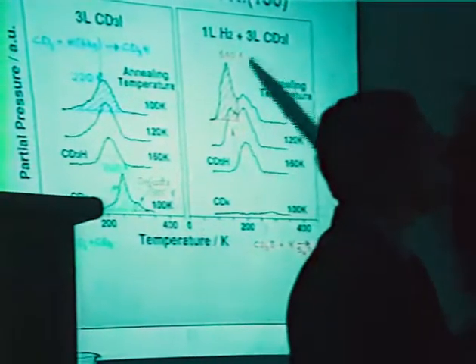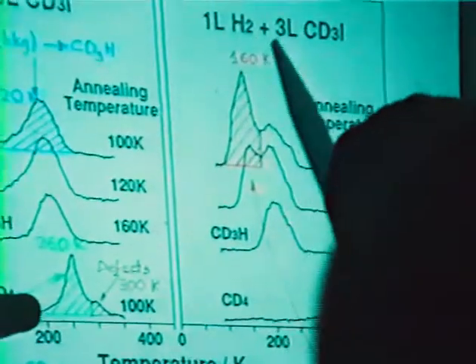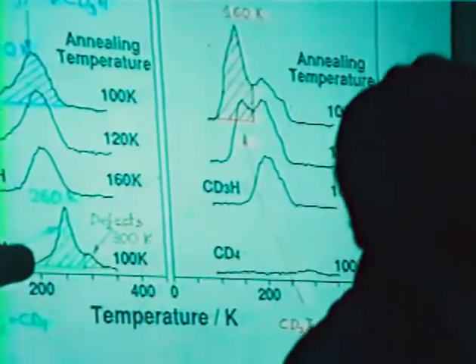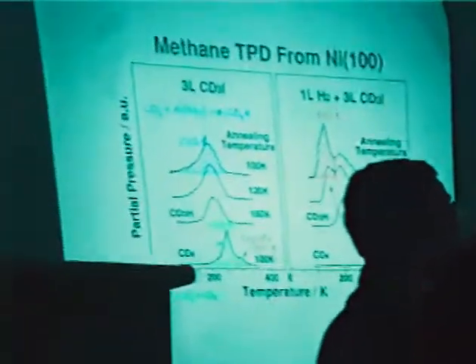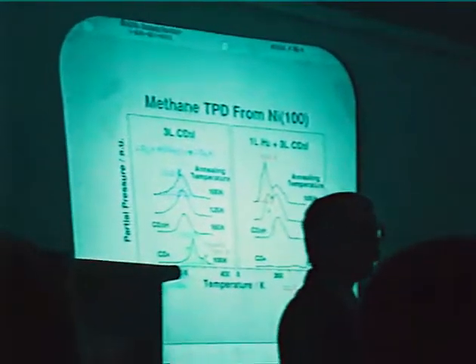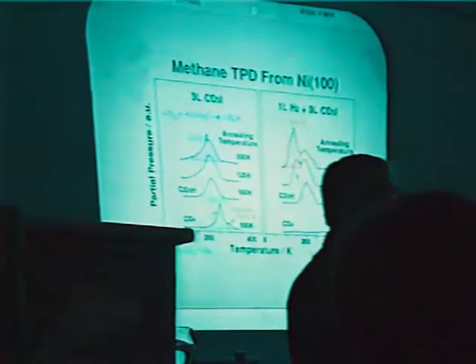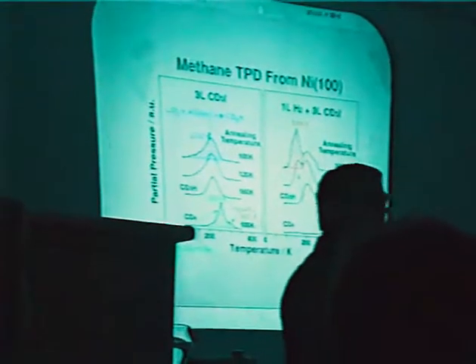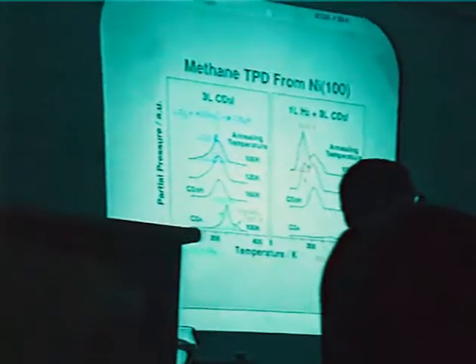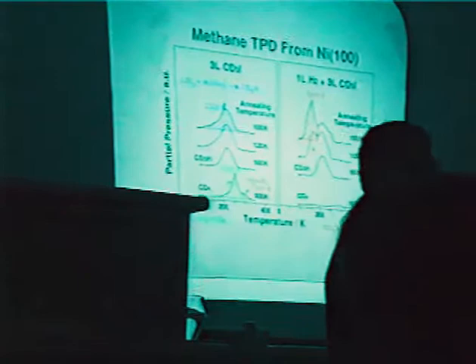We wanted to explore this hydrogenation reaction a little bit more in detail, and for that, we actually did an adsorption experiment in which we put the methyl groups, and now before that, we put the hydrogen on the surface. Instead of relying on having background hydrogen, we go and put hydrogen on surface. We saturate the surface with hydrogen, and then put the CD3I in order to enhance this reaction. And sure enough, you kill the pathway where CD4 is formed. No decomposition takes place. You can hydrogenate all the methyl groups before you get to this temperature, except for this little bump, which we associate with defects on the surface. So you do form CD3H exclusively. By the way, no hydrogen exchange is observed on this surface as well. So you see nothing else but CD3H.